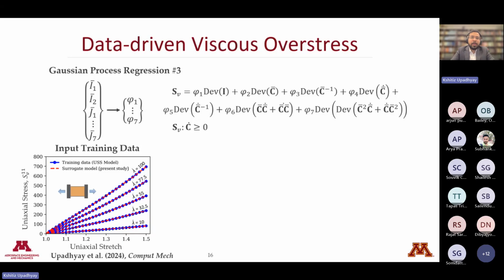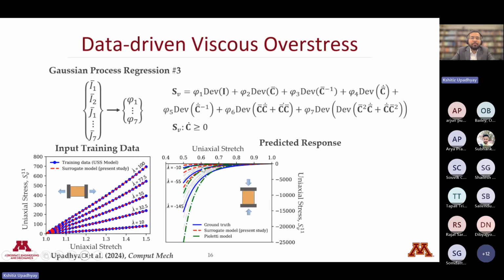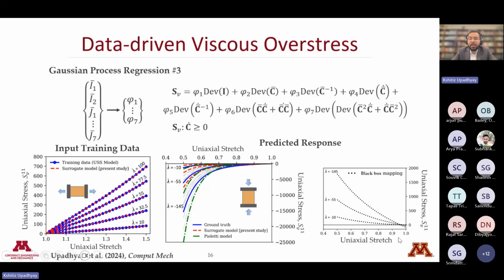All right, finally, let's look at the viscous overstress part of the model. Here, I trained the model using uniaxial tension data across multiple strain rates in tension, and then applied it to predict mechanical response under compression. And as expected, both the surrogate model and an analytical model, this time a standard model called the Pioletti model, predict reasonable responses under compression. Now, this time you don't even see the black box mapping model here because it was predicting a tensile stress under compression, which is totally unreasonable and impossible.